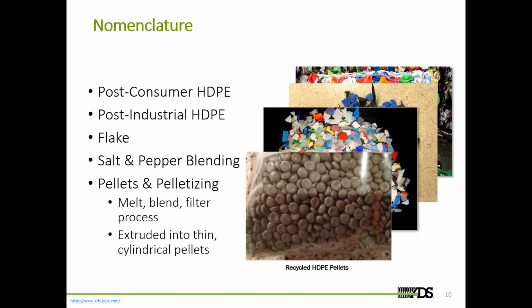What we also do is address one of the largest contaminants we have when making HDPE pipe, which happens to be polypropylene. The reason for that is that many of the items you recycle day in, day out, whether they're milk jugs or Tide bottles, the bottle itself, the jug itself, is made out of polyethylene. The cap is made out of polypropylene. And it's very, very difficult for us to hand sort those caps away from the jugs. One way that we're able to do that is after we process that material, we then melt it. Since polypropylene and polyethylene melt at different temperatures, we are able to melt filter out that polypropylene and then make the polyethylene that passes through that filter into pellets and make good pipe out of it.